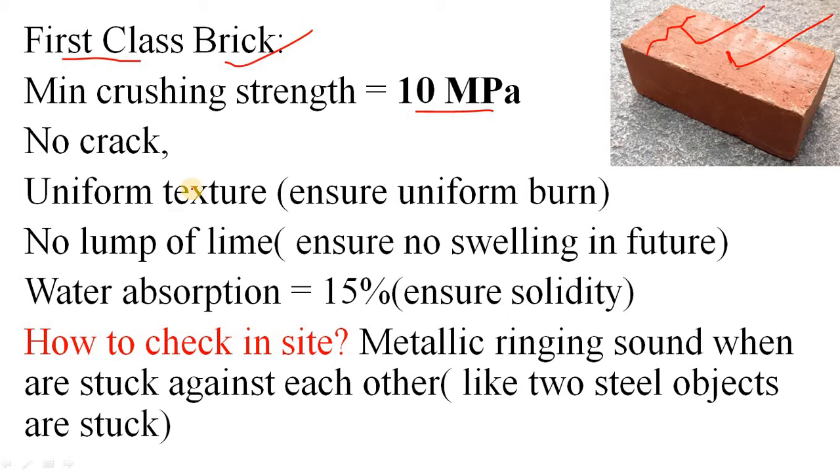As said earlier, the texture should be uniform - this ensures that the brick has burned uniformly. There should not be any lump of lime. Lime is a component of brick, and if there is excess lime or a lump of lime, in the future this lime gets hydrated and the brick actually splits. Why? Because when lime hydrates, it tries to swell, and obviously it applies tensile stress within the brick, and the brick splits.